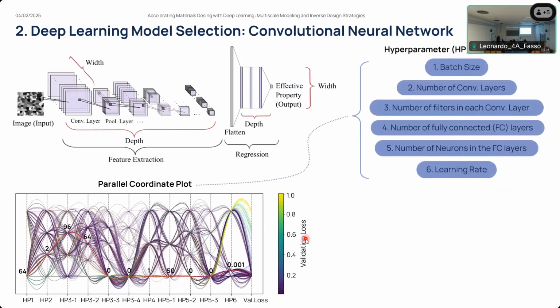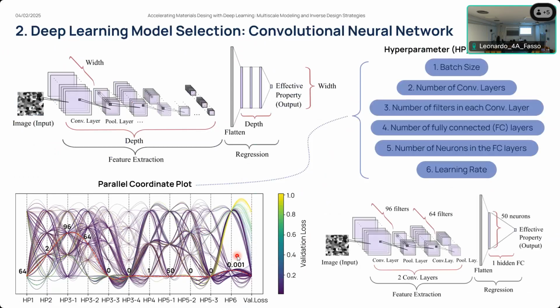Then, in order to determine which model we will use for our implementation in this study case, a hyperparameter tuning campaign is performed. This is important because when we train a neural network, there are internal parameters that are adjusted during the training process, but there are some parameters associated, for example, to the architecture or other aspects of the training that are not updated during the training, and we have to decide on them prior to the training. In order to optimize this architecture, this campaign is performed, and this is summarized in this parallel coordinate plot, where each line represents a different configuration for the architecture that we tried. From all the trials, we determine the best performing one, the one obtaining the lowest validation loss, and we select this neural network for the subsequent parts of the study for the results.